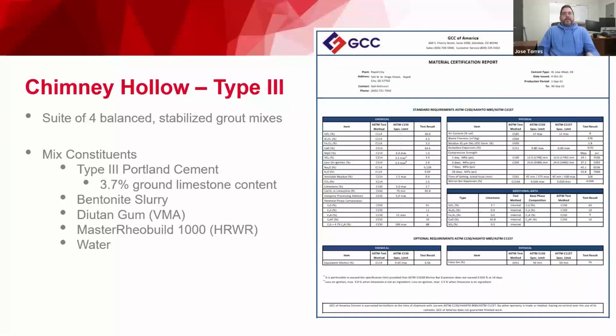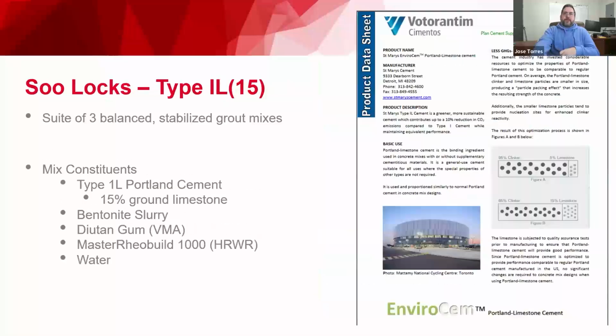The other job we're looking at is Chimney Hollow. There were about 4 balanced stabilized grout mixes, using type 3 Portland cement. I had a limestone content of 3.7%. Mix very similar here, the only thing is we switched out welan gum for diutan gum, just for availability purposes, and diutan gum is a little bit more robust.